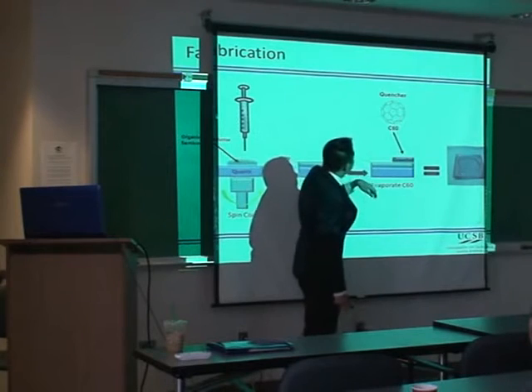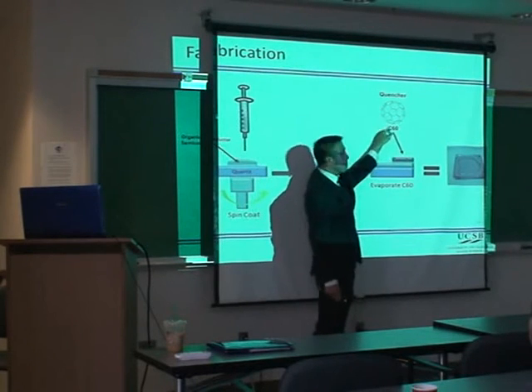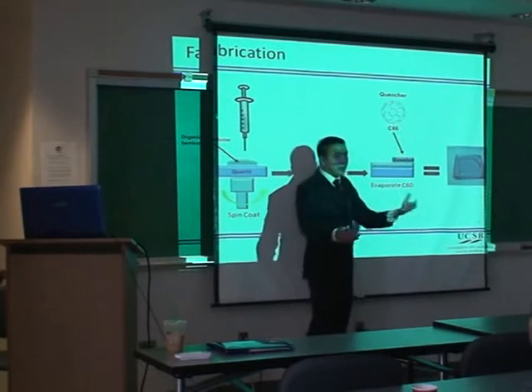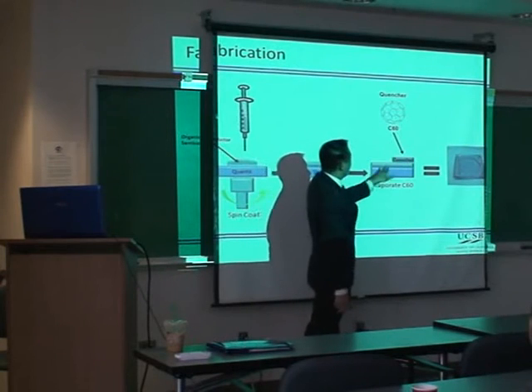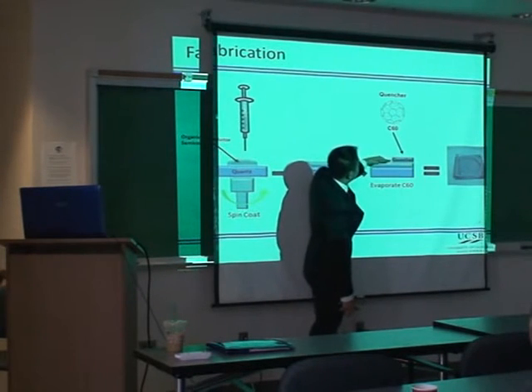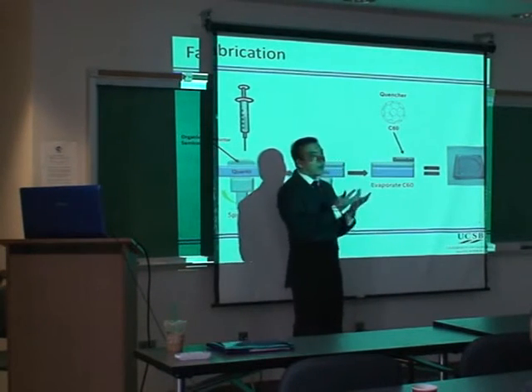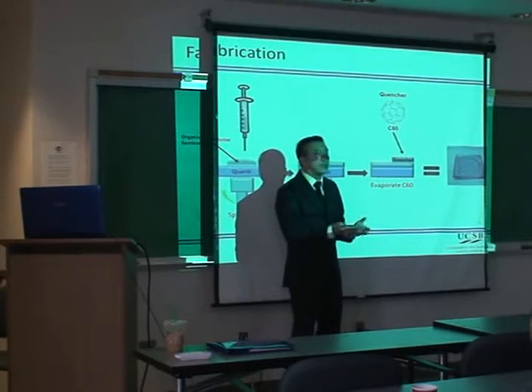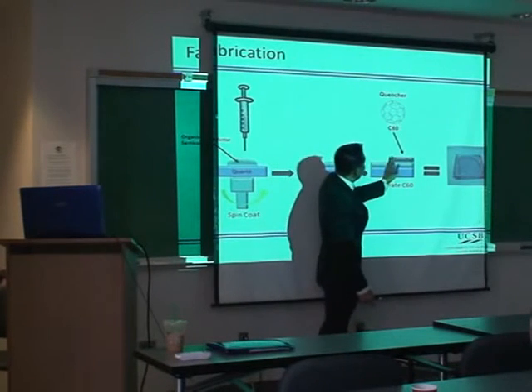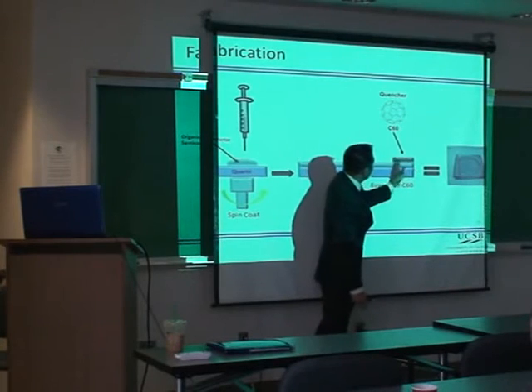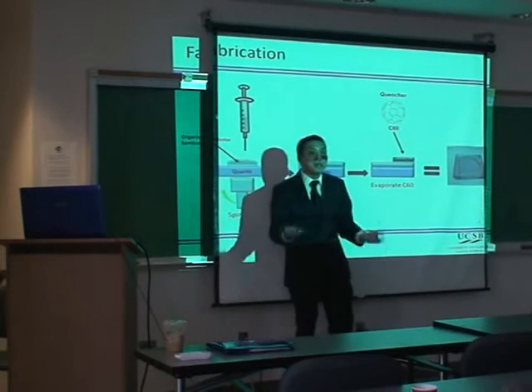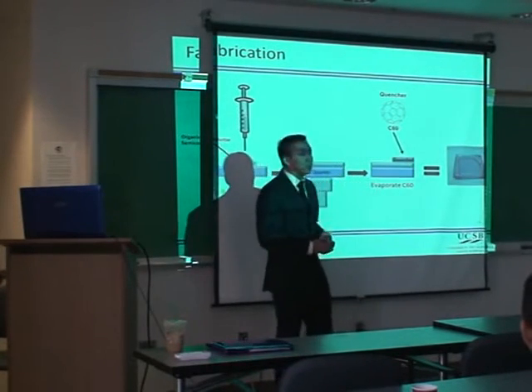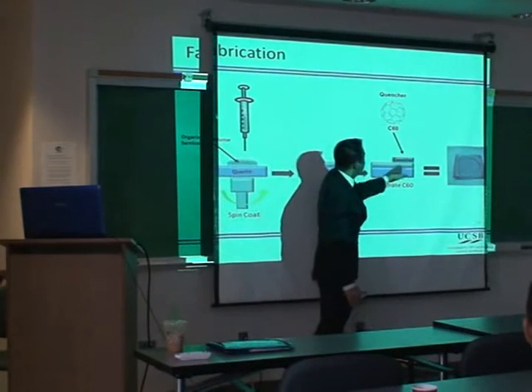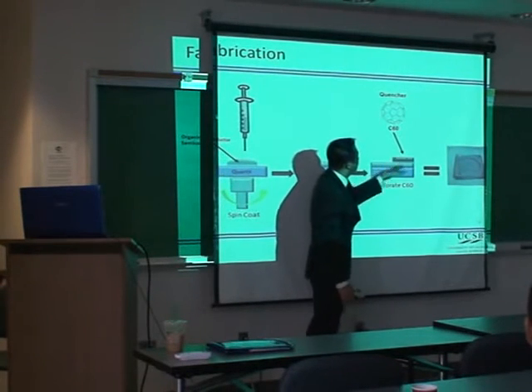We then have a very consistent organic layer on our substrate, and what we then want to do is add a quencher. So the quencher we use is C60. As I mentioned earlier, this accepts electrons. And what we do is we actually cover half the film, and we evaporate the C60 on our substrate. And what this does is that we have half the substrate that has the quencher and half that doesn't. So it reduces the amount of material we need and actually makes the study more consistent because we can compare the same thickness on both sides with and without the quencher.